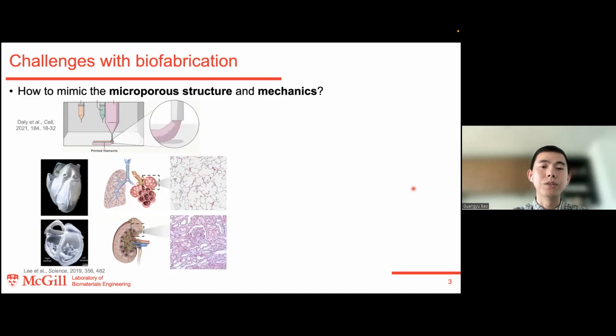In recent years, extrusion-based bioprinting has become a go-to technology for fabricating cell-laden hydrogels with complicated geometries. For example, the organ-sized construct, such as the heart shown here, is a demonstration of how powerful this technology is for shape control. However, one of the limitations of the popular extrusion-based bioprinting is its resolution, which is usually greater than 100 micrometers. The technology is not there yet to mimic the tens of micrometer-sized features, such as the pores in the lungs and also in the kidneys.